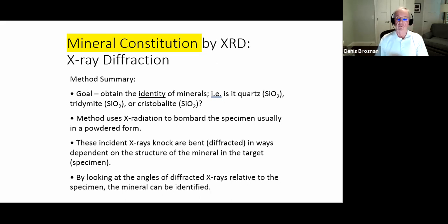Now, the chemistry is the chemistry, but it doesn't tell us the mineral constitution. To determine the mineral constitution, we need to use a method that's sensitive to the crystal structures of minerals that are there. And we want to identify the mineral. Quartz has three forms: alpha quartz, tridymite, a different structure, and cristobalite. And in ceramics, we're very interested in these substances because there's a volume transition when quartz is converted into tridymite and to cristobalite. There's a density difference between these minerals. The density of cristobalite is the lightest or lowest, so there's a big expansion in going to cristobalite.